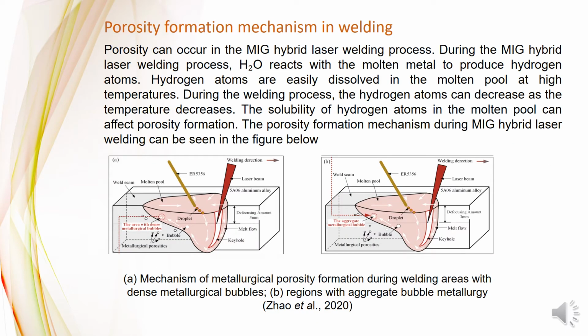Porosity formation mechanism in welding. Porosity can occur in the MIG hybrid laser welding process. During the MIG hybrid laser welding process, H2O reacts with the molten metal to produce hydrogen atoms. Hydrogen atoms are easily dissolved in the molten pool at high temperature. During the welding process, the hydrogen atoms can decrease as the temperature decreases. The solubility of hydrogen atoms in the molten pool can affect porosity formation. The porosity formation mechanism during MIG hybrid laser welding can be seen in the figure below.